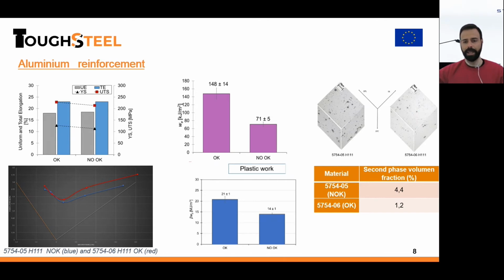This different behavior could be justified by taking into account the second phase volume fraction inside the alloy, so the intermetallic compound inside the two alloys. For the new chemical composition that allowed us to stamp the component, the second phase fraction is just 1.2%, while in the not okay it is 4.4%. So this means that in the previous alloy, the intermetallic compound is higher than in this one, and could have a strong effect on the plastic work and on the essential work of fracture.